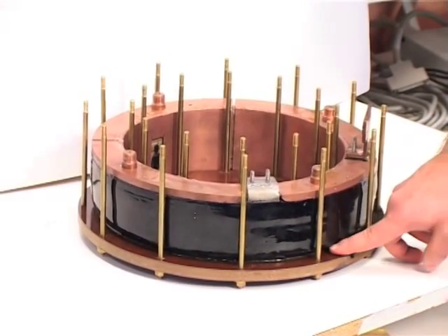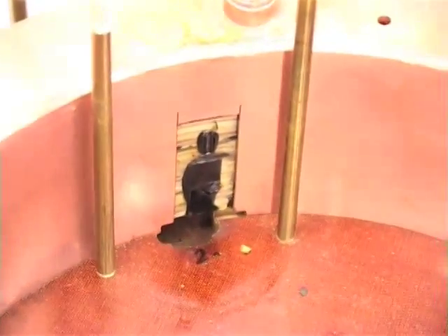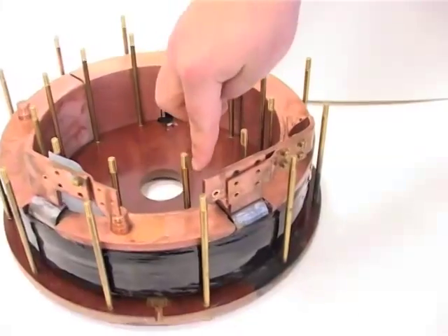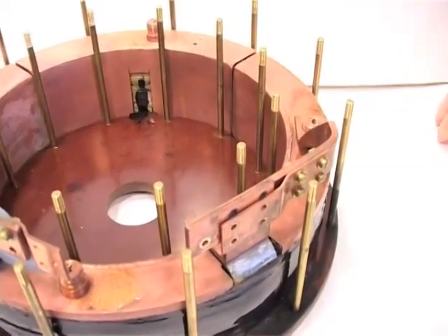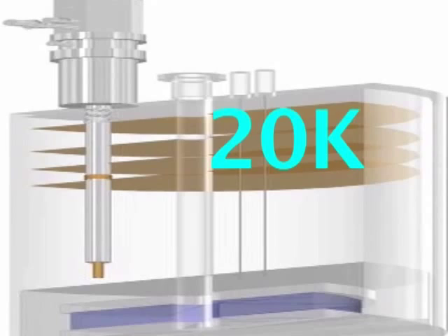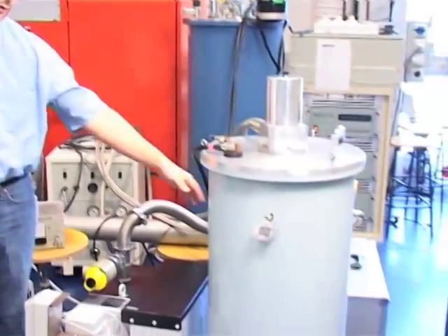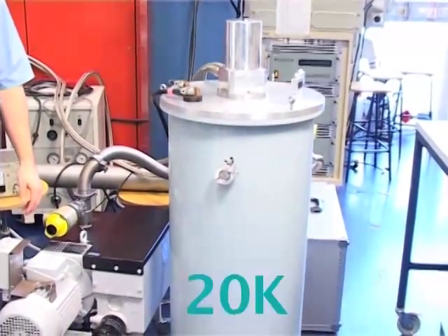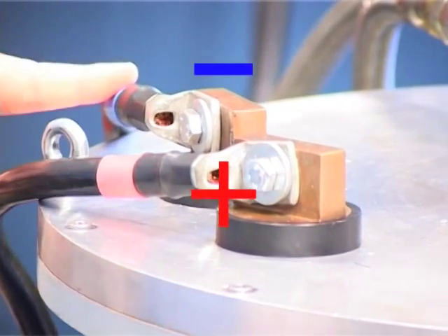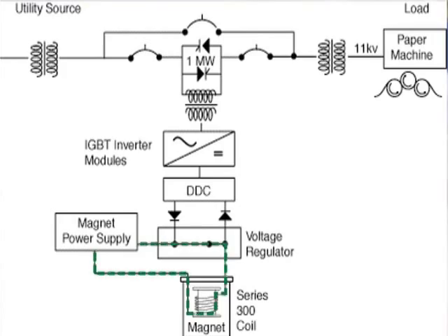The magnet is consisting of 11 pancakes made of bismuth. In here we have HTS leads. And obviously the HTS leads have to be cooled down to maybe 20K. This coil can store as much energy as 5 kilojoules, and it's inserted into the cryostat, where it is cooled down to 20K. This is a DC system. As you can see, there are plus and minus terminals in the top of the cryostat.